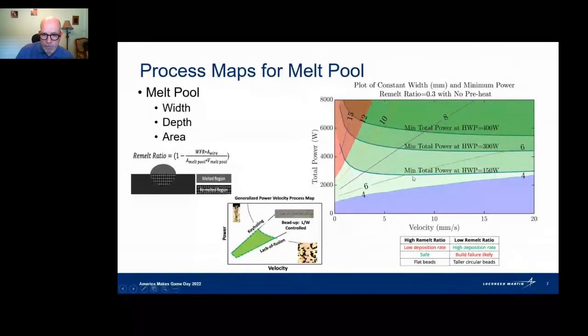And what these contours are meant to define is there are regions outside of this green highlighted area where you will either get a keyholing effect, that you're dumping too much energy into the part, or you'll get a dripping boundary. So for a given hot wire power along one of these contours, if you get below that contour in this range, what will happen is you'll start dripping wire into the melt pool, and you'll end up with an unstable build. And so there's some significance to that you'll see further on in the presentation. So keep that in mind when it comes to that.